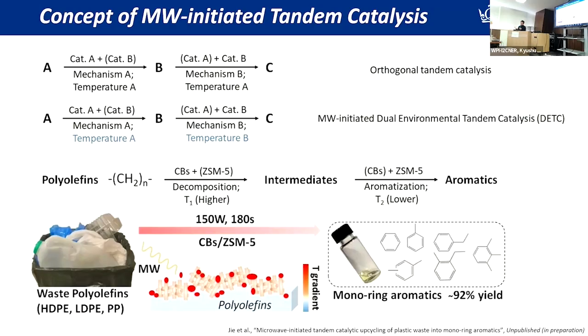But in comparison, the ZSM5, the zeolite, didn't heat very well in the microwave. So they are naturally creating a temperature gradient between each other, and they are responsible for different parts of the reaction. For example, the polymer decomposition will primarily be carried out on the carbon black, and once the intermediates are formed, they will transfer to the zeolite with its structured and catalytic properties. They will form the monoring aromatics, and we have now achieved over 92% yield of these BTEX.